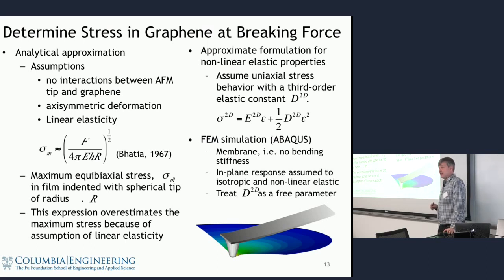In 2D, this turns out to be a sweet spot for doing mechanical testing, because what we could do is clamp at the edge here. So this is a finite element simulation of the stress in the material as a function of position as we do this indentation. What you can see here is that the stress is concentrated just at the area around the tip. Away from the tip, at the edge, the stress is very low, and that means even just the weak van der Waals force of the graphene adhering to the SiO2 surface is enough to hold it in place. It also means that we're not going to fracture at our clamp, because we have a large area clamp that the load is distributed across a very large area.